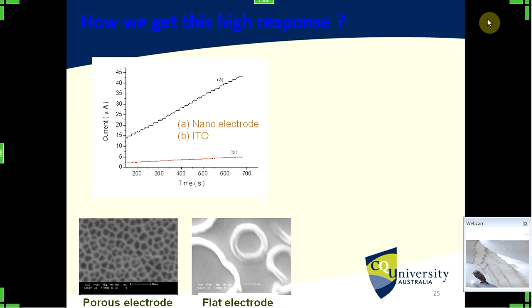Just to compare what happens, nanotube array electrode. This is the response we get from a planar surface. The most common planar surface you can find in a lab is ITO, indium tin oxide, which we use to make these screens. Even if you put it into a scanning electron microscope, you cannot see any difference. It's so flat. So we use that one as the conducting substrate with the same amount of platinum sputtered onto it and polypyrrole deposited, and these are the responses. High sensitivity to glucose.